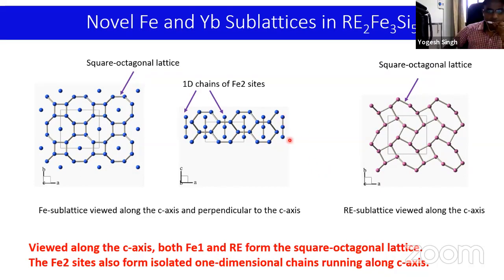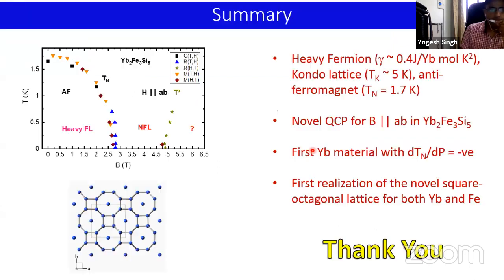So these 1D chains of irons, which are very isolated from each other, might themselves show charge density wave-like features, which we are exploring. Okay, so this is my summary. The ytterbium compound that we have studied is a heavy fermion material with a very large Sommerfeld coefficient. It is also a Kondo lattice with a Kondo temperature of about 5 Kelvin, and it undergoes antiferromagnetic ordering of Kondo reduced moments at 1.7 Kelvin.